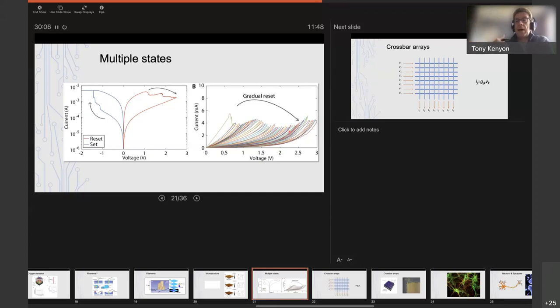devices that have maybe an analog variation of resistance, and we can cycle between these different states many, many times. And in fact, we've got up to 10 million times. Some of our devices have cycled 10 million times, and they still function. So we can go far more than that. So that's all very interesting. That tells you a little bit about the materials side of this and what's happening in materials and how we can vary these electrical characteristics.